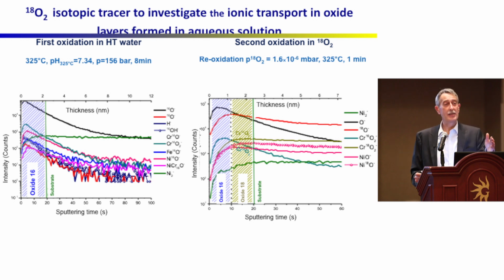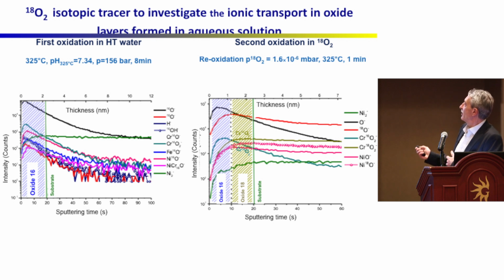So we can precisely locate the interface. So if we do that as a function of oxidation time in high temperature water, we have the kinetics of oxidation. We can analyze the oxide by combining XPS and ToF-SIMS. Now to look at the ionic transport, in the ToF-SIMS, we re-oxidize this with oxygen 18. And then we look at the profiles, and we can see that all the species containing oxygen 18 are found in this part of the layer.